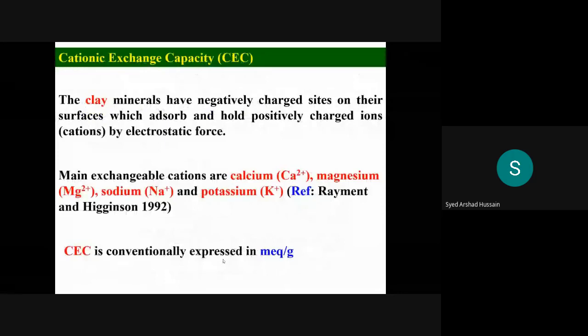And the clay minerals have negatively charged sites on their surface. This also absorbs and holds positively charged ions by electrostatic interactions. And main exchangeable cations are calcium, magnesium, sodium, potassium, etc., present on the clay surface or in between the clay layers. And CEC, or cation exchange capacity, is conventionally expressed in milliequivalent per gram.